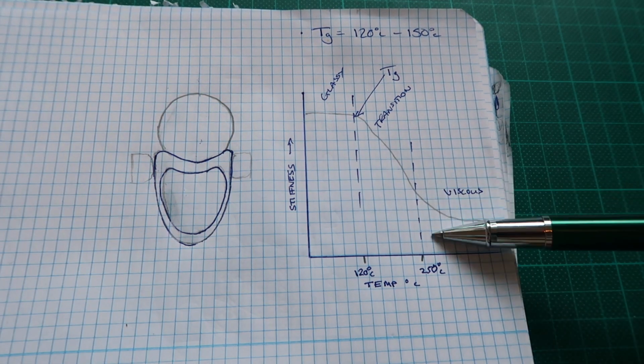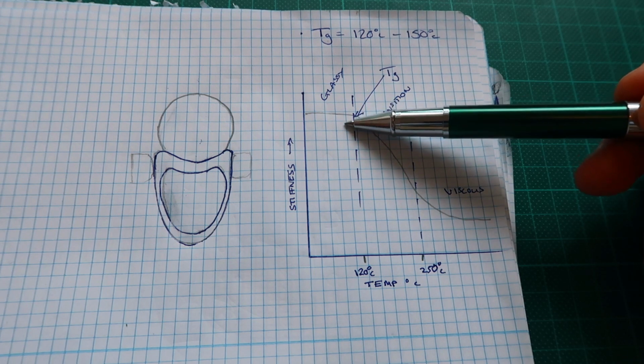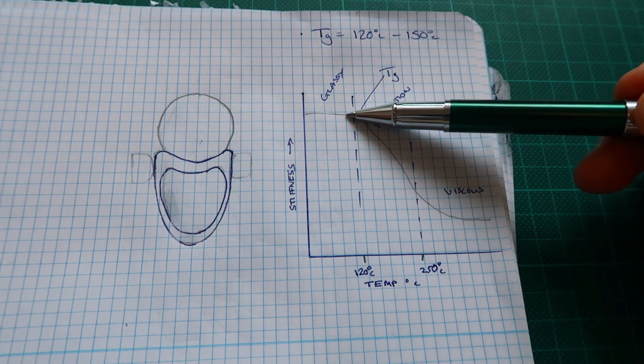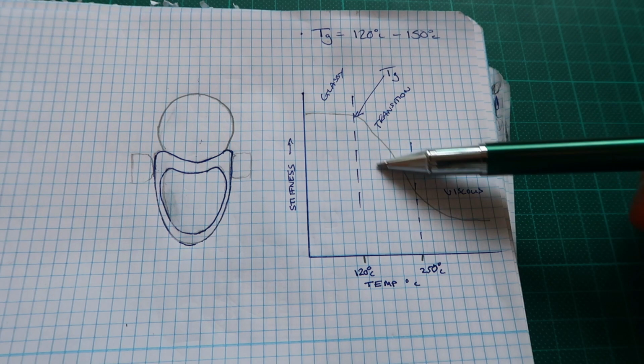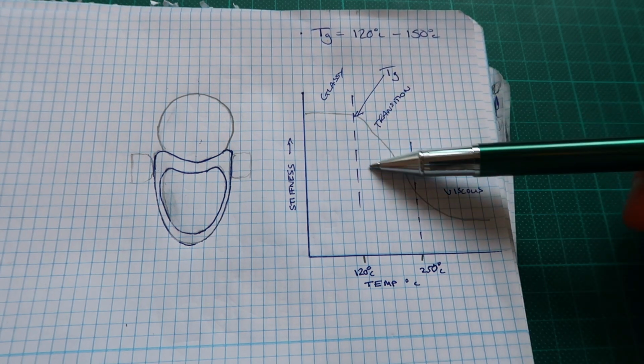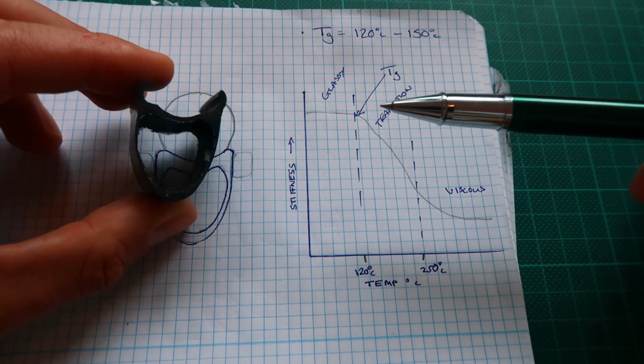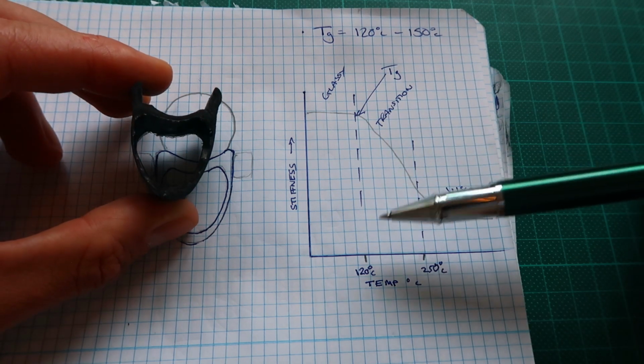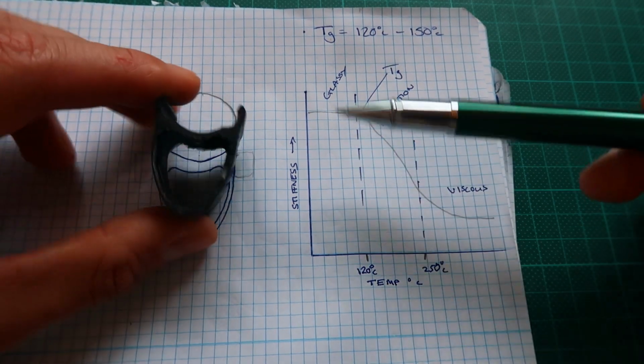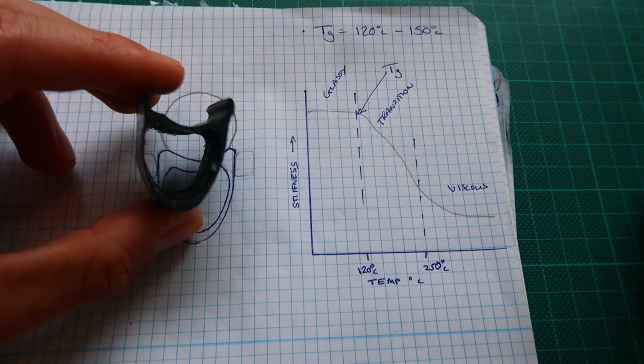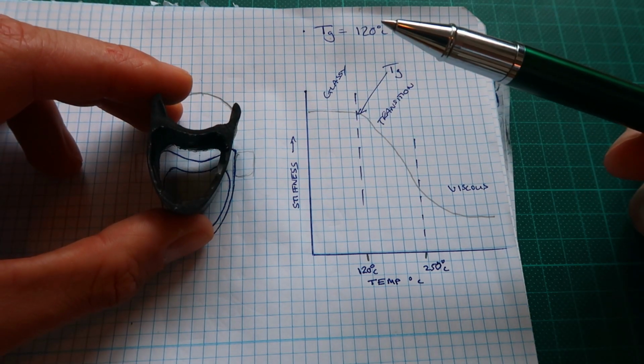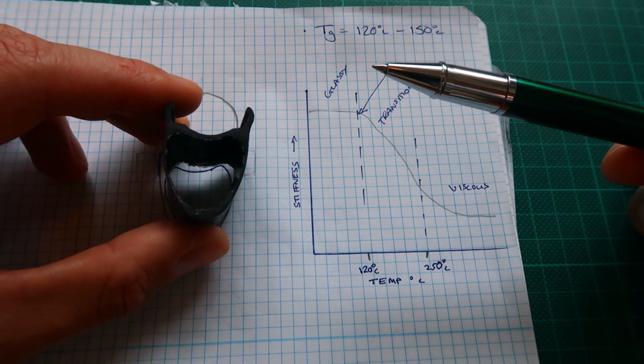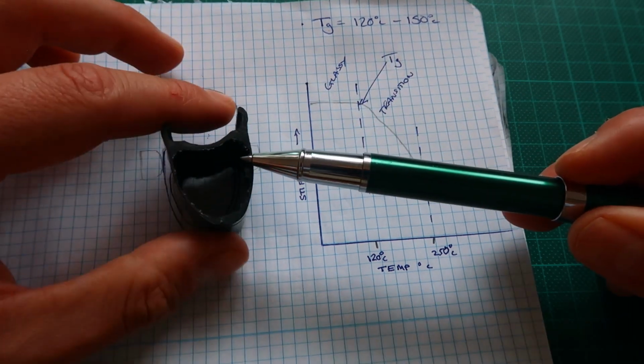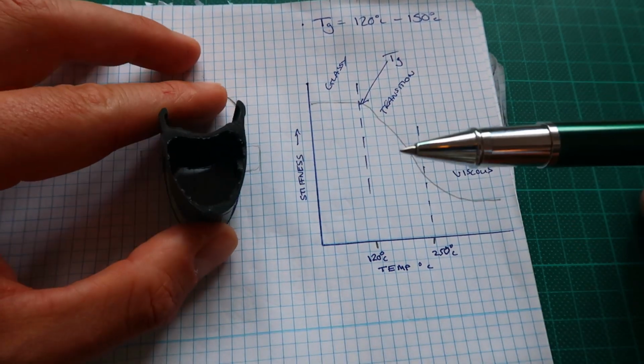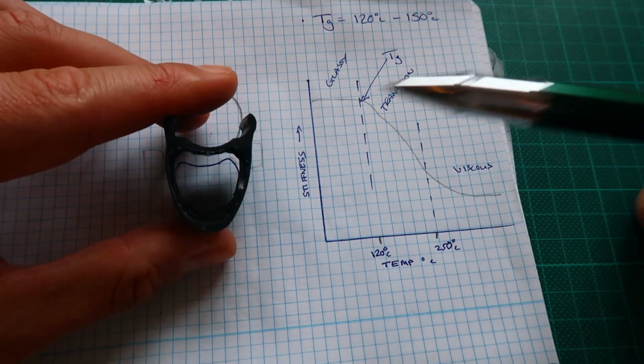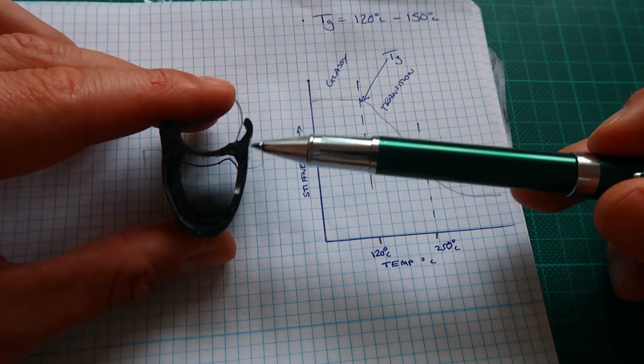Now, I'm not saying we've got up to this temperature, but even if you get to say 100, your slope is tending downwards, and you get to this big transition area where you lose a lot of the stiffness in the sidewall, and you really are at the mercy of whether the tyre is going to pop off or not. Hopefully in this case it didn't, and we caught it just in time. But what I'm saying is, these are flawed structures, so if you use carbon clinchers, just be careful basically. Don't bomb down hills and jam the brakes on from high speeds if you can avoid it.